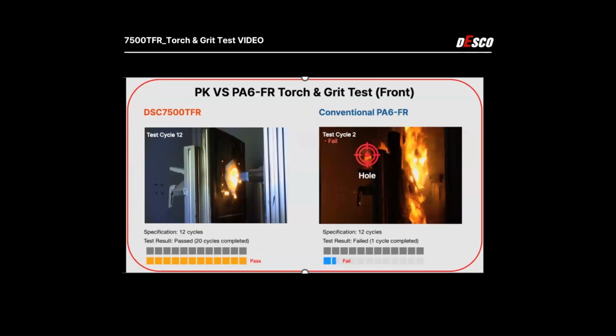Okay, now I'm going to show you a video of the torch and grit test featuring our 7500 TFR grade. To give you a clear comparison, the video will show two materials side by side. On the left is our TFR grade, and on the right side is a standard flame retardant material, a polyamide 6 with 30% glass fiber rated to V0. Both specimens are, as I said before, 2 millimeters thick, with a 1,200 degrees Celsius flame, 6 millimeters back between the specimens and the torch. Let's watch how it will work.